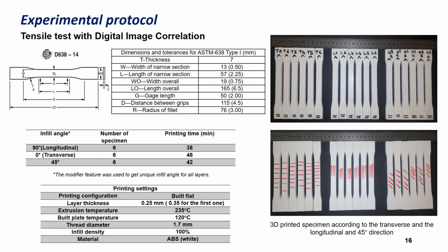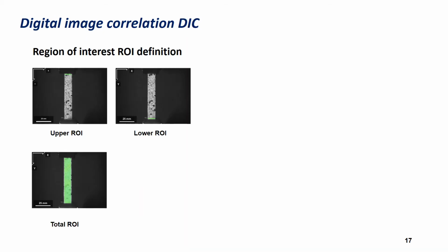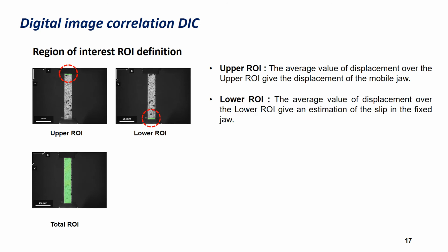Here we start by printing tensile specimens according to the transverse, the longitudinal and the 45 degrees directions. White ABS filament was used in order to have a better contrast while applying the black speckle. For every tensile test, three regions of interest will be selected. A method was used to access the true displacement of the specimen. Here, we note that we were confronted with numerous slip problems and filament delamination inside the jaws of the machine.